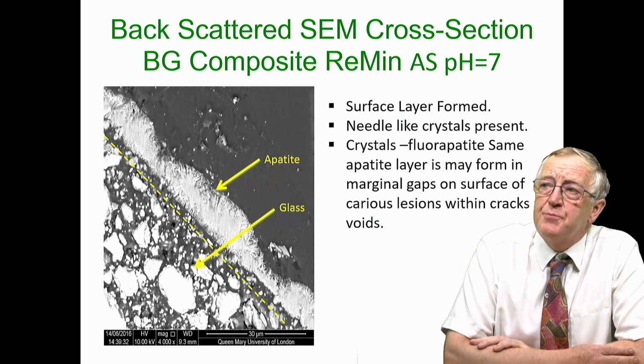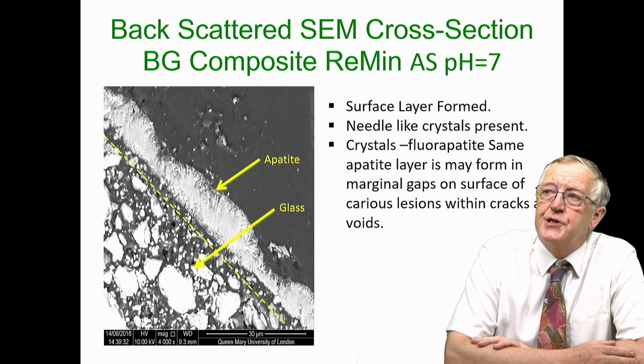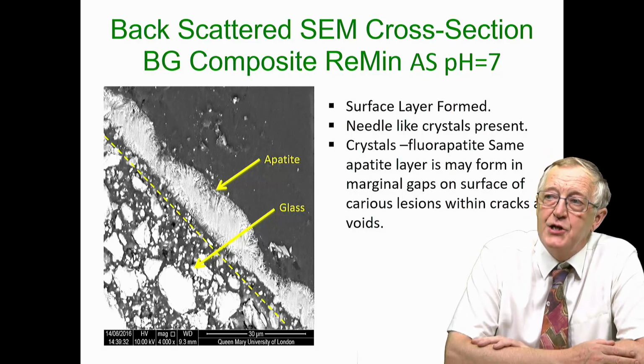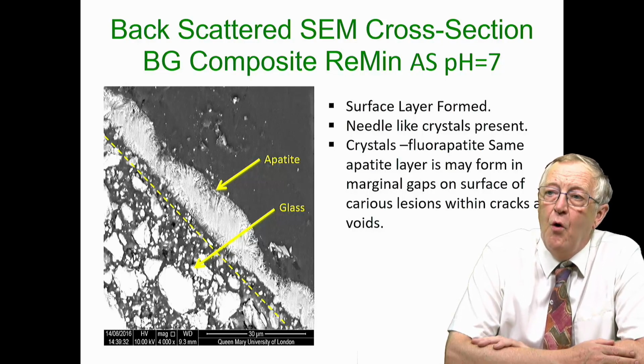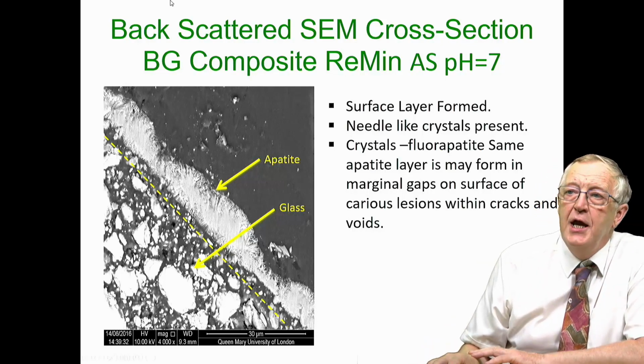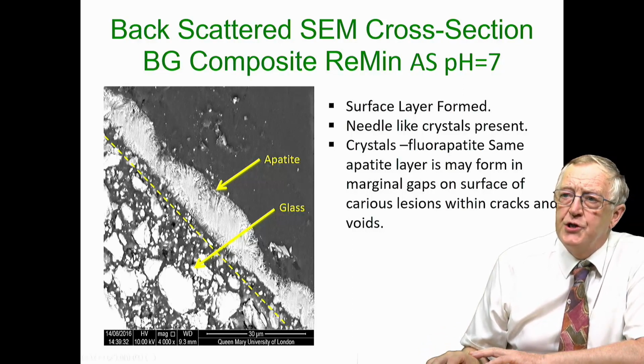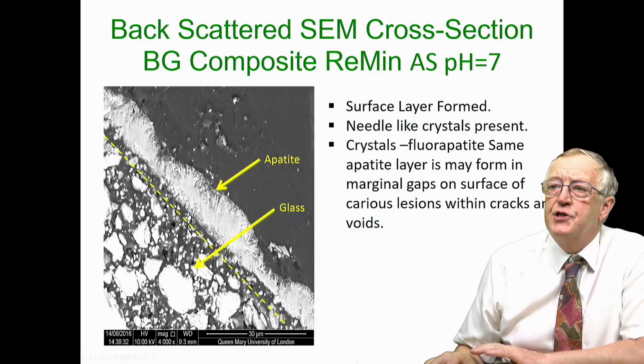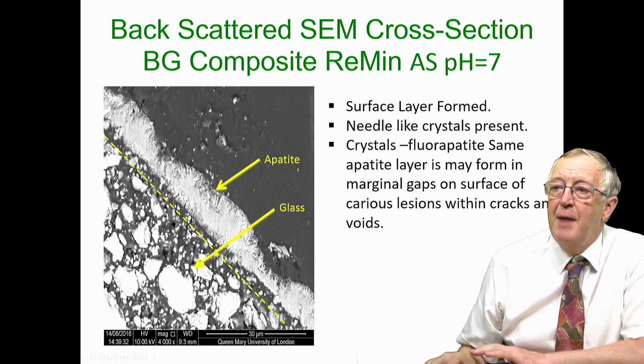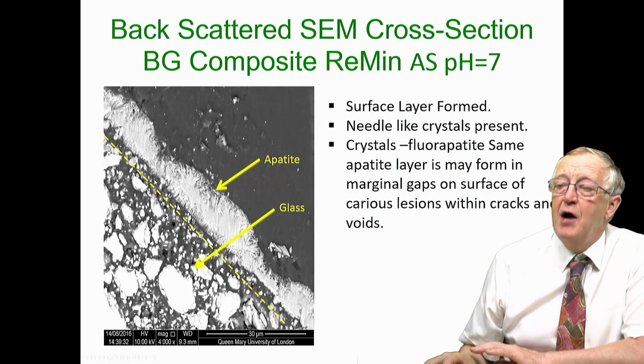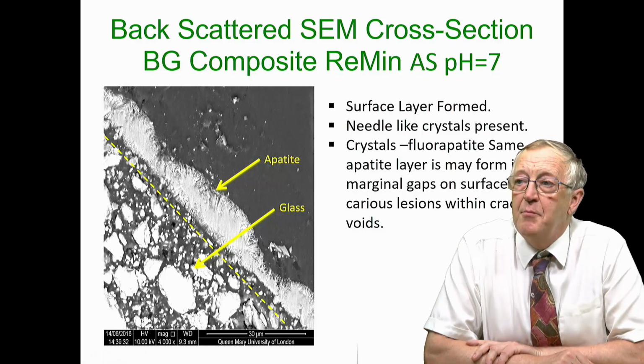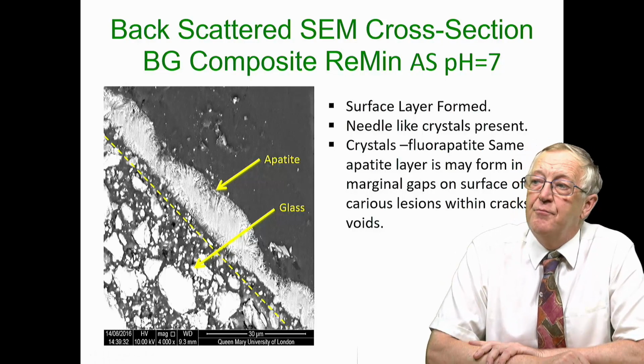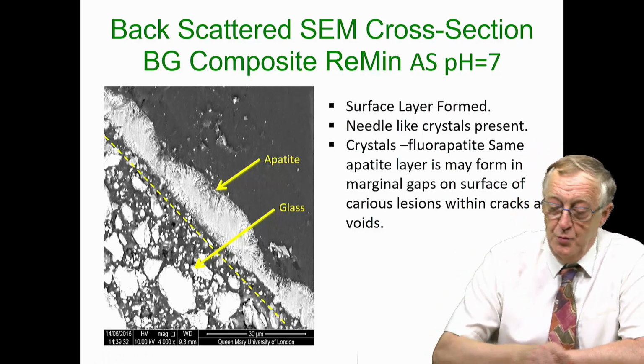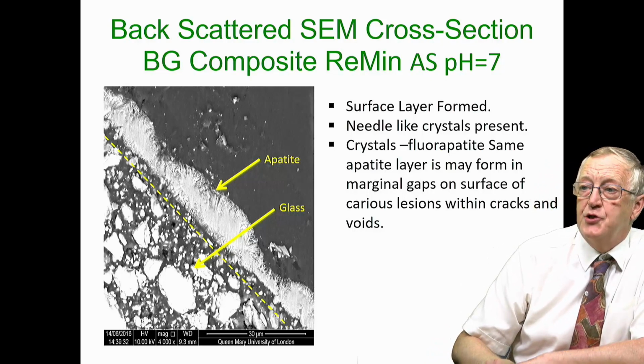If you do the same experiment, but you now immerse the disc in artificial saliva at pH 7 rather than pH 4, what you can now see is this white deposit on the surface of the disc. And if you look carefully, you can see some needle-like crystals of apatite. The reacted layer in the glass surface is now much thinner. It's only about 5 to 10 microns thick. And this is the effect of pH on the glass degradation, which occurs much more rapidly at acidic pH.